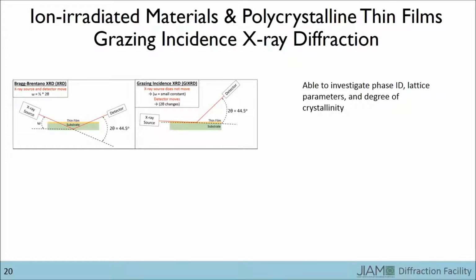If your sample is a thin film on a substrate or an ion-irradiated material, conventional Bragg-Brentano XRD may probe too deeply beneath the surface for you to study the region of your material that is interesting. As shown in the left panel, the X-rays interact with the substrate much more than the thin film, which is reflected in the diffraction pattern as a weak contribution from the thin film and a strong contribution from the substrate. With knowledge of the expected composition and density of your material, however, we can estimate the penetration depth of the X-rays as a function of omega, which is the angle at which the X-rays strike your sample. This helps to ensure that you only study the depth of your sample that is most interesting to you.